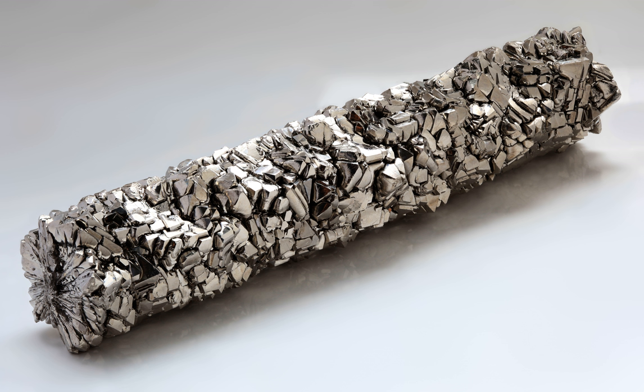At 550 degrees Celsius (1022 degrees Fahrenheit), it combines with chlorine. It also reacts with the other halogens and absorbs hydrogen. Titanium is one of the few elements that burns in pure nitrogen gas, reacting at 800 degrees Celsius (1470 degrees Fahrenheit) to form titanium nitride, which causes embrittlement.